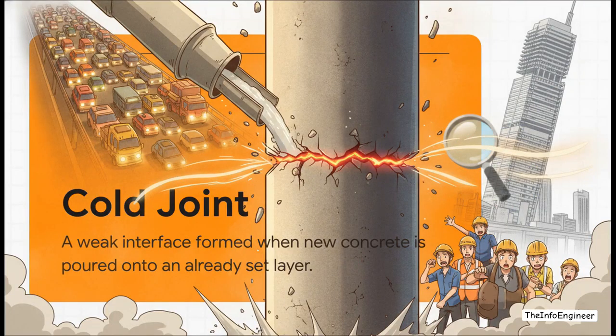Okay, so what happens if that hydration process gets interrupted? Say a truck gets stuck in gridlock and the concrete that's already sitting in a column begins to set before the next batch even arrives. Well, you get what engineers call a cold joint. This is a severe structural defect. It's essentially a seam where the old concrete and the new concrete simply refuse to chemically bond. So instead of a solid, single monolithic pillar, you've effectively built a crack right into the structure. Under lateral loads, think heavy wind or an earthquake, this weak interface completely ruins the column's shear resistance. It's a catastrophic failure waiting to happen.